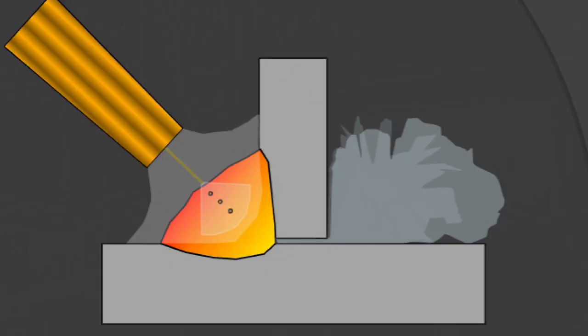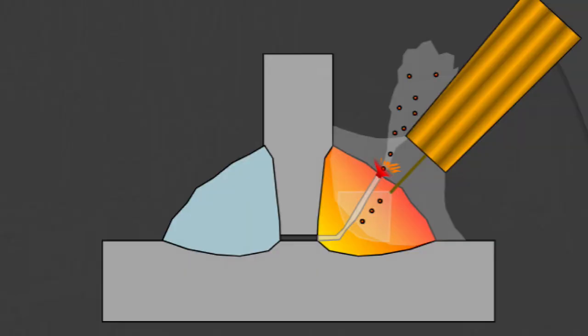The pinholes will usually show up on side two of the joint. And the reason for that is simple. When I weld the first side, the paint is being burned into a hot gas, and that gas can just escape through the crack. It's a T-joint, there's a crack there, where they come together. And that hot gas can just escape out through the back side. When you weld the second side, there is no escape. So the gas tends to come out through the weld and it will bubble and propagate up through the weld. So the second side will tend to have a lot of pinholes.